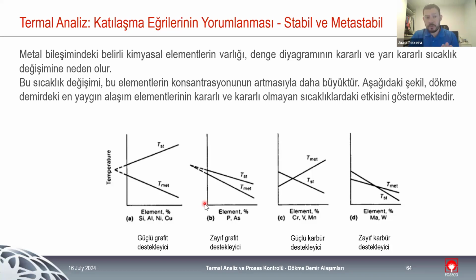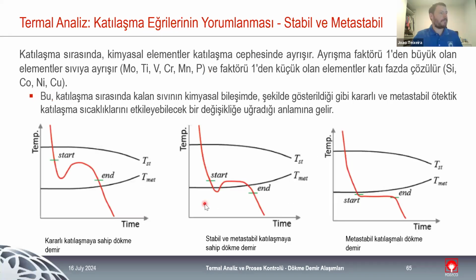We have the carbide promoters, chromium, vanadium, that have a high affinity with carbon and can steal the carbon and transform carbon into carbides. And we have weak carbide promoters like tungsten and other elements that carbon does not have a high affinity with, so they don't affect the ability of the carbon to transform into graphite.